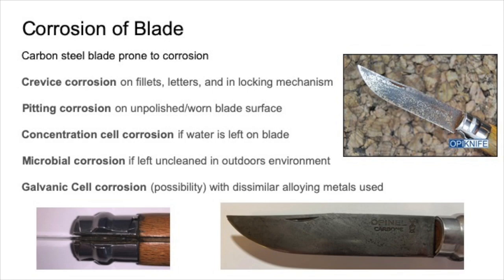Pitting corrosion can be seen in the top right-hand corner, all along the surface and in the fillets of the blade. This is usually due to an unpolished finish or a worn surface. Concentration cell corrosion is the underlying mechanism of the above two methods mentioned, and it can be simply formed by having water left on the blade, which isn't uncommon, especially in outdoor environments. Microbial corrosion can also form and can attack the metal both chemically as well as electrochemically. Galvanic cell corrosion isn't seen too much on this knife because of the use of similar metals.